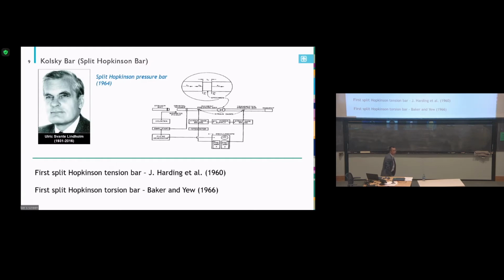But the Hopkinson bar was still used only for compression tests. They can only compress the sample. Then in 1960, Harding and colleagues developed the first Hopkinson bar version for tension. Several years later, Baker and Yew developed the first torsion bar. Basically, dynamically, we can compress it, we can pull it, and we can twist it. So we calculate material properties under different stress states, like uniaxial compression, tension, and torsion.